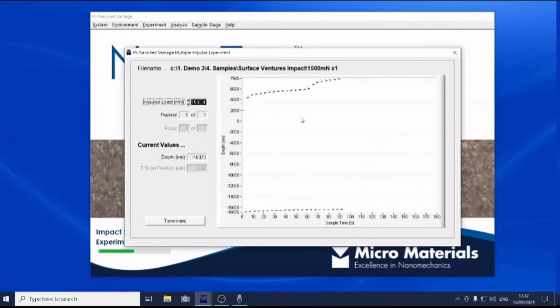So what we often tend to do with this technique is we configure multiple repeats at various different loads, and then we perform some statistical analysis on the resulting data in terms of the scale of the depth of the initial impact event, in terms of the depth of the final impact event, etc. And actually, I think in another part of today's session, some of that results analysis will be covered. So we've got about another 50 seconds to complete, and then we will move the sample back to the optical microscope, and we'll be able to take a look at our impact test site and actually look at the fracture event that's taken place.